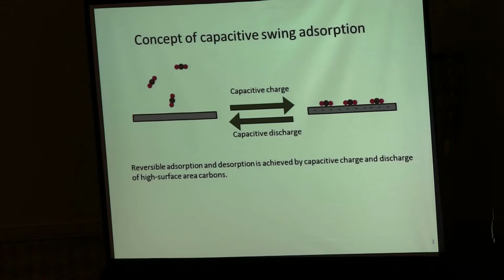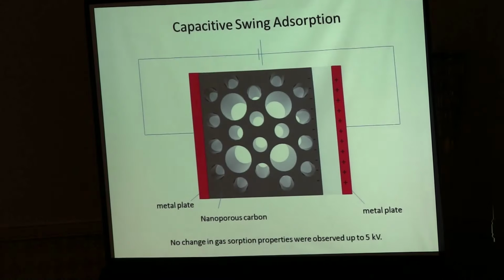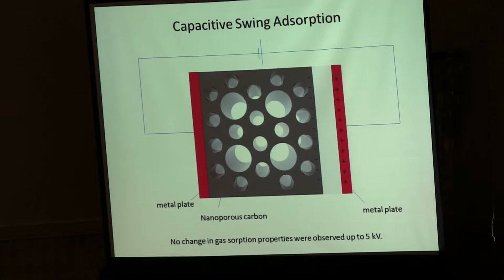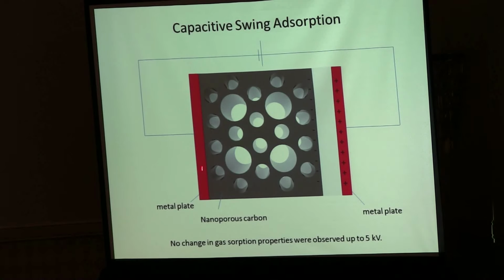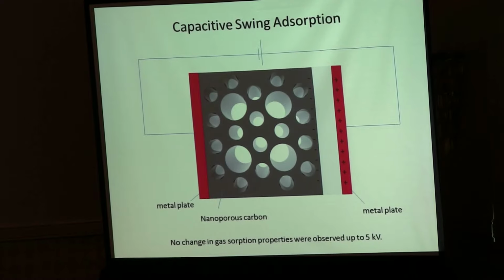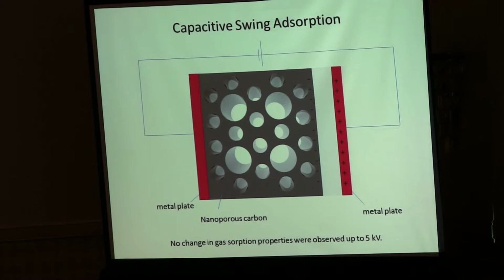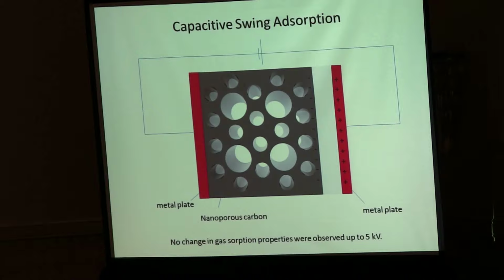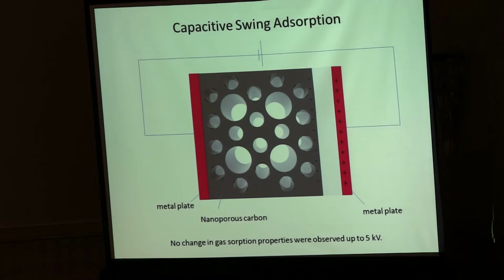So to test that hypothesis, we have first built a parallel plate capacitor. We have prepared a nanoporous carbon monolith and connected it to a current collector on one side, and left an air gap between this carbon material and the counter electrode on the other side. Then we applied a high voltage. We went up to 5 kilovolts and investigated whether there actually would be a change of adsorption properties.